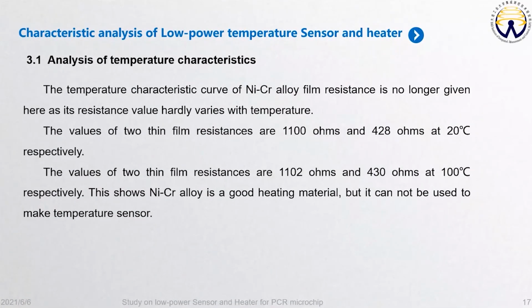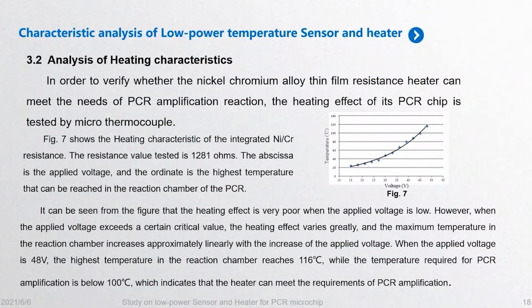The temperature characteristic curve of nickel chromium alloy film resistance is no longer given here, as its resistance value hardly varies with temperature. So this shows the nickel chromium alloy is a good heating material, but it cannot be used to make temperature sensor. In order to verify whether the nickel chromium alloy thin film resistance heater can meet the needs of PCR amplification reaction, the heating effect of its PCR chip is tested by microthermocouple.